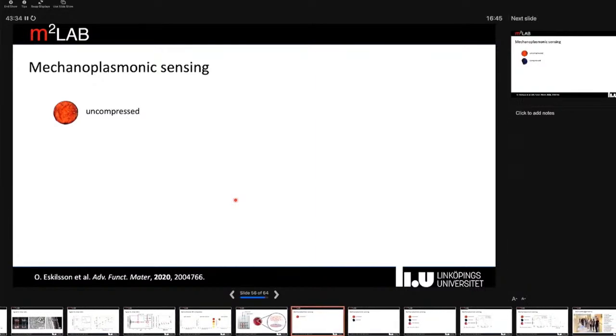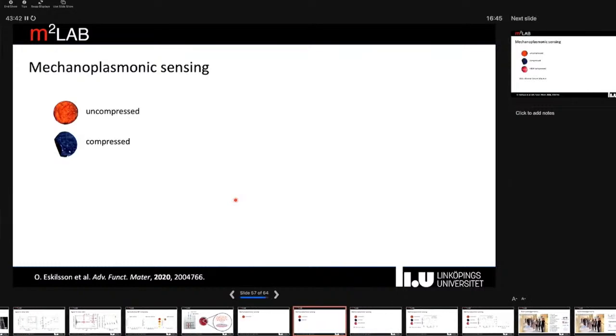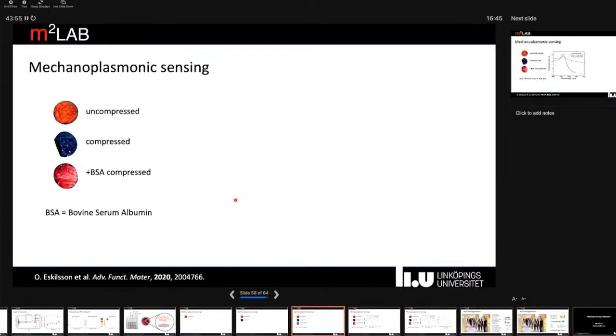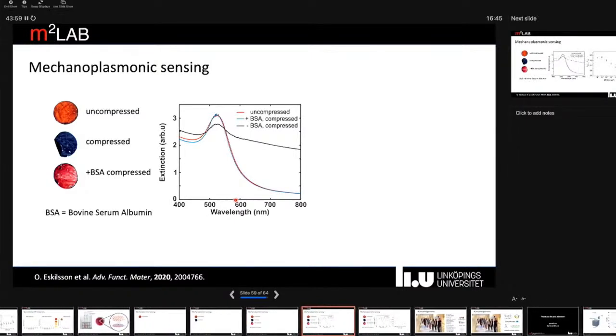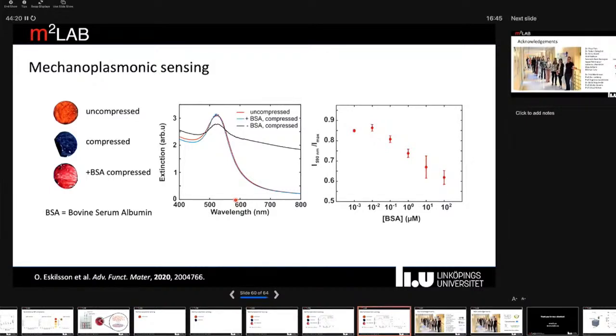And we started exploring what could essentially influence this mechanoplasmonic coupling. So when comparing an uncompressed material with a compressed material, we see quite distinct color differences. But if we immobilize a protein, just by physisorption, on the particles before we compress, we don't see much of a color change. So essentially, the proteins here can prevent the particles from being mechanically forced into contact. So by using mechanical pressure, we can sense what goes on at the nanoparticle surface. And also, reasonably, the more proteins you have on the surface, the more efficiently these proteins inhibit this mechanoplasmonic response. So we can also get a concentration-dependent response.